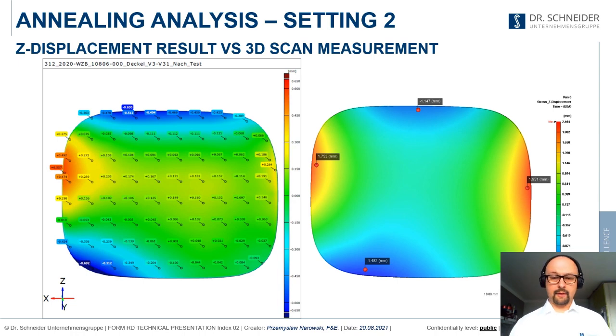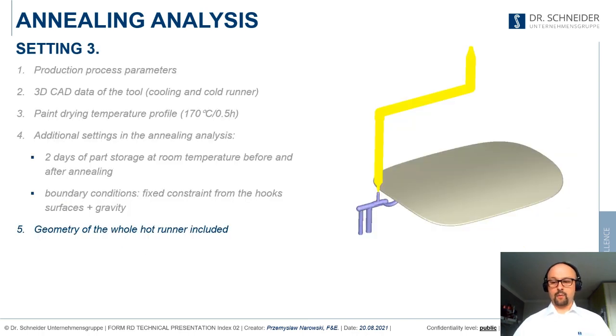As you probably remember, here was something like 2 and something millimeters. Now it's 1.9. Here was 1.9. Now it's 1.7. So we are 0.2 millimeters better than we were before, which is still not satisfying for our purposes. So what can we do more? We can make another complication in our model, introduce more data. The only thing we could still introduce at that moment was the hot runner geometry.